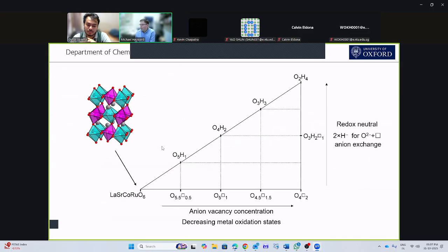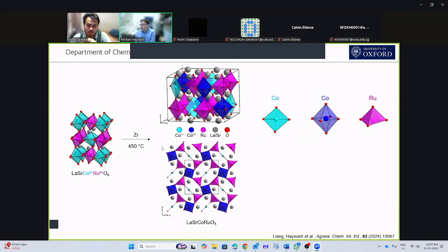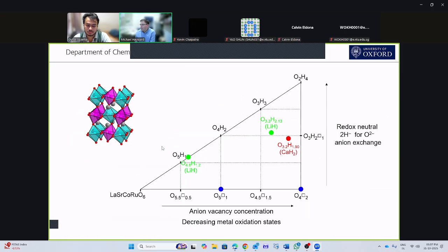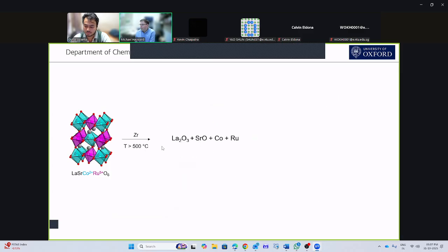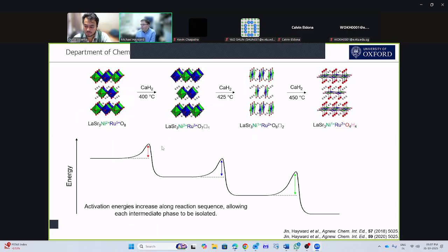So where are we? If we think about this sequence here, so we go from the O8 to the O7 to the O6 to the O4H4. In that reaction process, you can't really isolate pure O7 or pure O6 because if you're trying to make O7, you always get a bit of O8 and a bit of O6 present because that step is a bit of a blur.